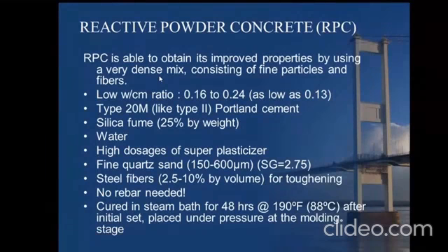And generally reactive powder concrete cannot be made as a normal cured concrete. You need temperature curing in order to achieve this strength. Not only steam curing, sometimes we also require pressure. So generally we go for an autoclave process wherein temperature and pressure enable the hydration reactions to take place faster. Right. So these are some of the major points that have to be noted in the manufacturing of reactive powder concrete.